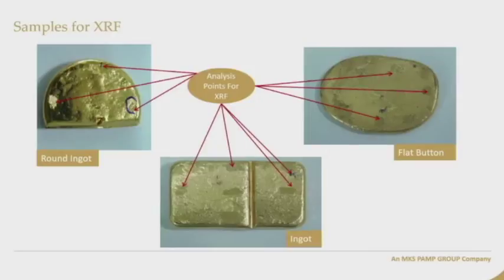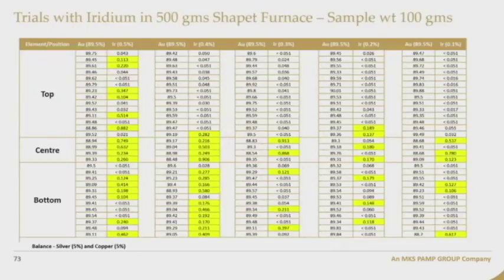So as Pankaj explained, we did the XRF analysis, and we tested on the top surface, the bottom surface, and also we cut the metal into half and checked at the cross section. This is typical data which we had analyzed. What I would like to do is explain this chart so that subsequent charts are easy.